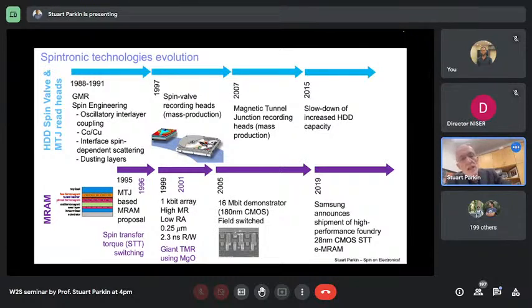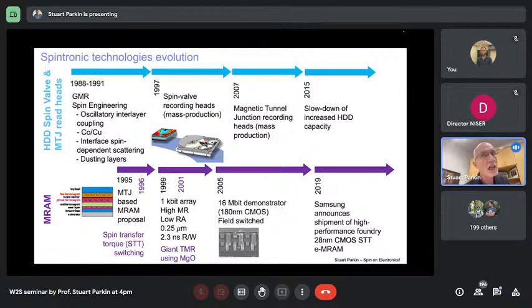What I wanted to point out here is that if you look at the top, I want to show you over time the discoveries we made in 1988 and 1991 enabled us to propose a spin valve sensing device, and it only took a few years, 6 years after I made these discoveries, the materials, the oscillatory interlayer coupling, the interfacial nature of the spin-dependent scattering that gives rise to giant magnetoresistance. All of these ideas, dusting layers, were used in the very first spin valve device in 1997. As mentioned, 10 years later, the devices switched to magnetic tunnel junctions, but essentially the same kind of structures.